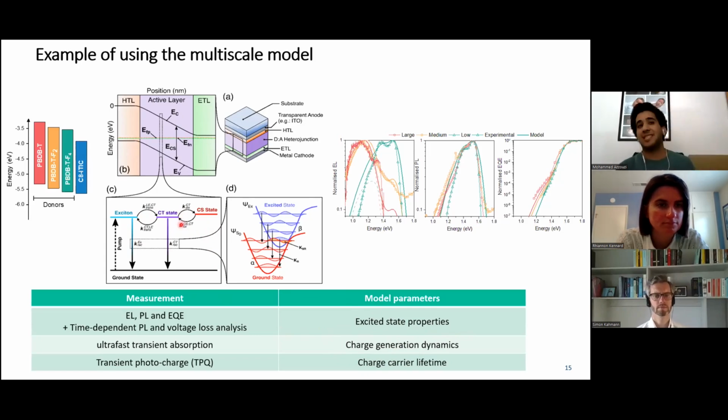And normally we don't really see the recombination in the ultrafast time scale, and we can use transient optoelectronic measurement in the microsecond time scale to gain some information about the recombination, and therefore extract this reformation rate from the free charges, like electron and hole or CS state, to the CT state. And to do that, I'm going to mainly present transient photocharge, which is a technique similar to TPV, but we've shown that it's more reliable to use on low mobility systems such as organic semiconductors.